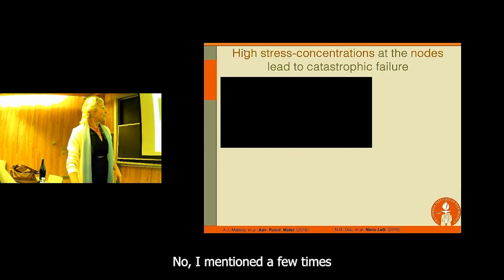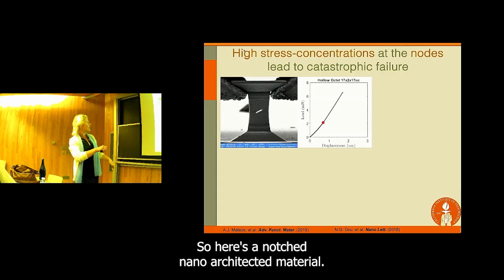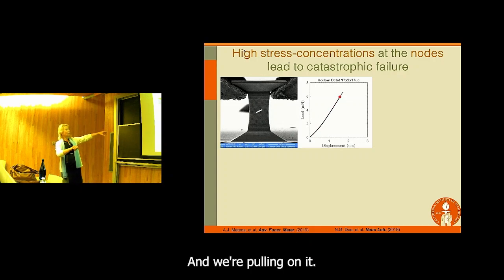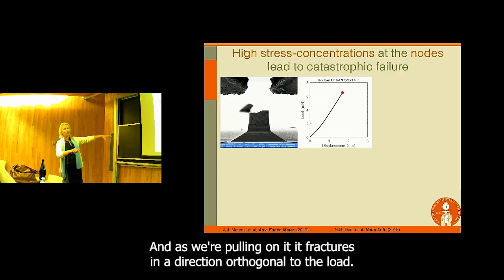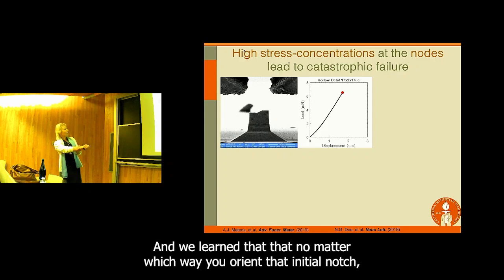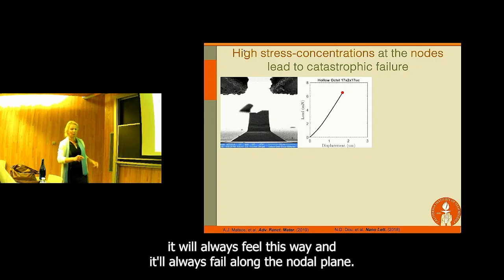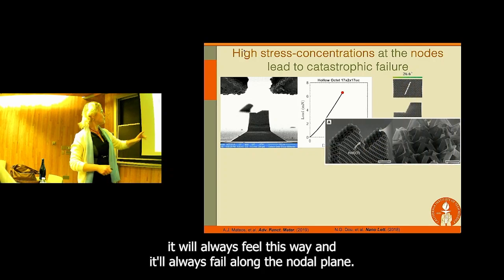Okay. Now, I mentioned a few times the importance of the nodes, and that nodes are kind of bad news. I want to really show this to you in our tensile experiment. So here's a notched nano-architected material, and we're pulling on it. As we're pulling on it, it fractures in a direction orthogonal to the load. And we learned that no matter which way you orient the initial notch, it will always fail this way, along the nodal plane.